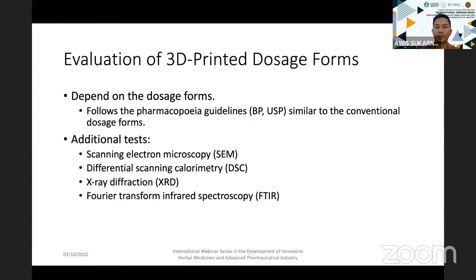Or sometimes when you mix it together with the polymer and then run it using the DSC, you can see the polymer has a transition temperature of, for example, 150 degrees, and let's say the drug has a melting point at 100 degrees. Once you combine them, you find the melting point suddenly disappears and the transition temperature moves slightly lower, maybe 140 instead of 150 degrees. This is because sometimes the drug itself will affect the transition temperature of the polymer. So that's why it's good for you to have the DSC study.